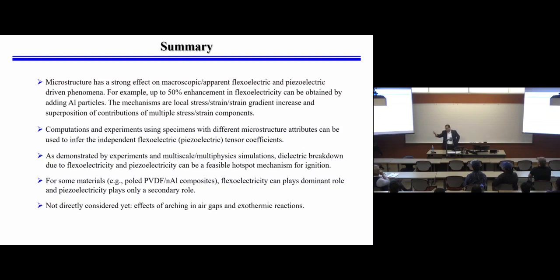Positions of the voids or particles, for that matter, cannot be controlled. When you make these materials, they are random. Locally, it matters a lot for a particular point. But if you talk about a large enough area, then it's the aggregate behavior that matters. Still, when you change their locations, the overall behavior will change a little bit, right? So my idea of handling it is, we know that each random realization, what people call an instantiation, is going to give you a slightly different result, right? There is nothing I can control. Nobody can control. So the way we handle that is, I analyze enough of those random samples, so I know the range.